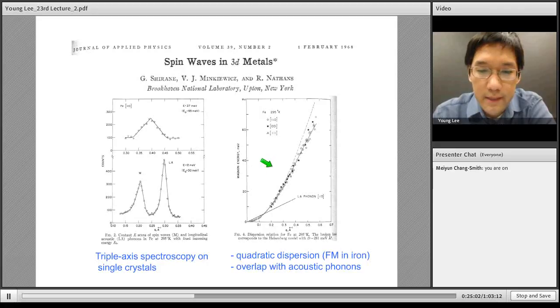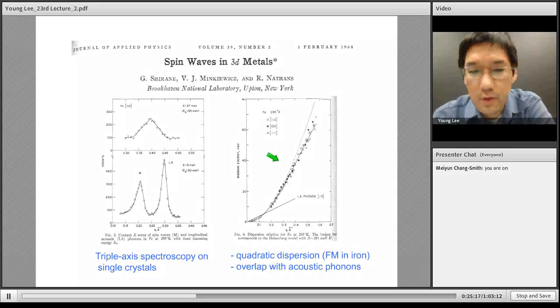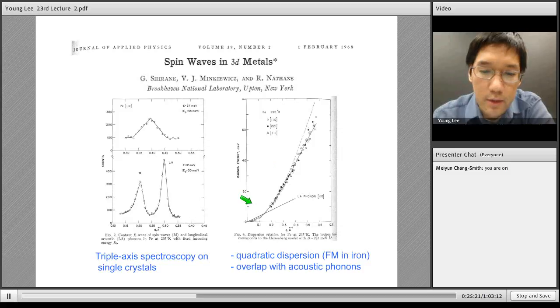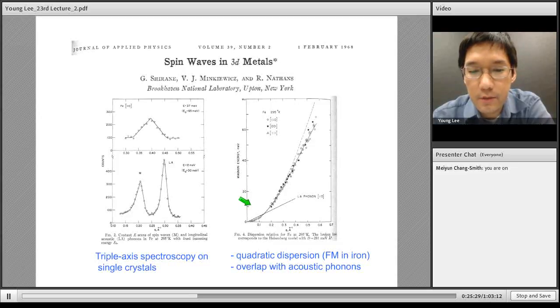And when they plot the data, that is just due to this spin wave mode. Here, they show that what you have is a quadratic dispersion at low Q, and then going up to higher energies, it starts to fall off this quadratic dependence, which we do expect. But you also see that you do have this overlap with the acoustic phonons down here, so you have to do some work to distinguish the two.